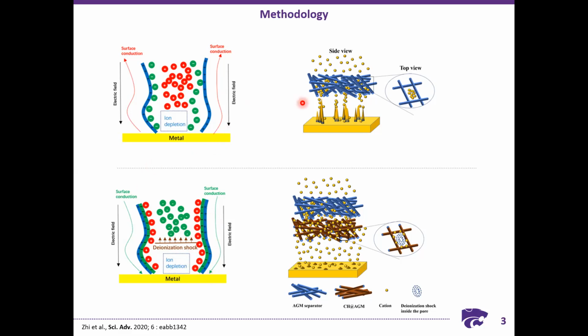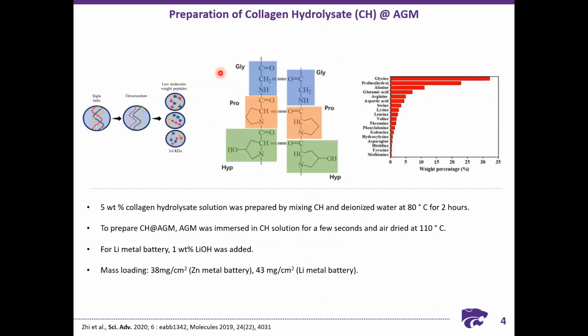Whereas without the interlayer, this surface conduction will happen in the opposite direction because of the positively charged AGM separators. So here only the anions will be in the diffusion layer, while for the cations, surface conduction can happen in the opposite direction. So the limiting current will be lesser than the limiting current that can be achieved by the diffusion-controlled process.